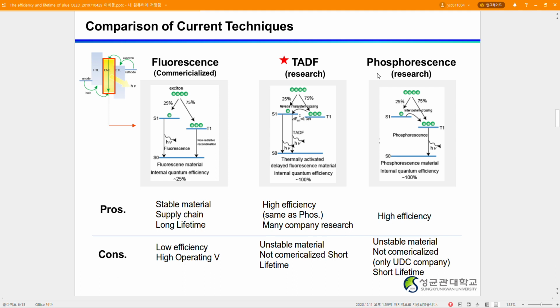In blue phosphorescence OLED, TTA involves the energy of two triplet states fusing together, resulting in an exciton in a higher excited state, which causes low efficiency. In research on blue phosphorescence material OLED, when triplet excitons combine with polarons, they create a hot excited state which is larger than the bond dissociation energy. This effect is so-called roll-off, generally occurring at high luminance. So device lifetime is the most important issue in phosphorescence blue devices.